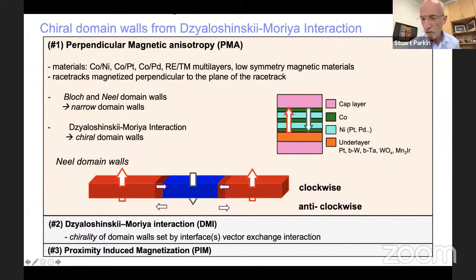And this was a subject that was really extensively studied 30 years ago. And a wide variety of magnetic multilayers display this property. That's important. But at the same time, for racetrack, what is particularly important is that you build this heterostructure on an underlayer, shown here in orange, which is formed from a heavy metal, for example, platinum or tungsten. And then you break the center of symmetry of the system, so that this can give rise to several effects.